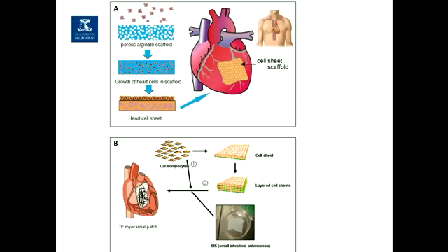I think I mentioned before, you can only grow things so thick before the cells in the middle no longer get any nutrients without a blood supply. So that's the same for tissues in our body, but it's also the same for growing tissues in a lab. It's around 200 microns. So if you're growing something that's roughly around 400 to 500 microns, to around half a centimetre, depending on how porous it is and how much media or nutrients can infiltrate through and how much waste can release out. If you have something that's quite dense and you don't get that diffusion of nutrients, you'll get a necrotic core inside. So by creating individual cell layers, putting them on top and then putting them into a patient is one way to do this.